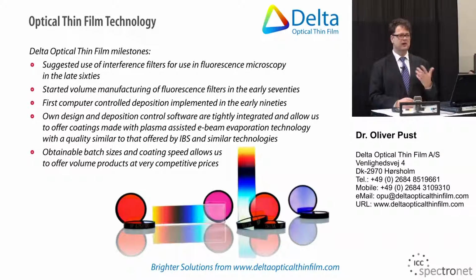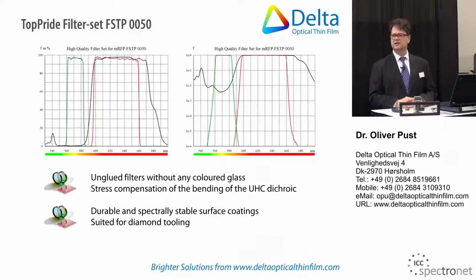Before I show you LVF filters, I can't spare you from seeing some of our high performance fluorescence filter sets. On the left-hand plot you see a typical fluorescence filter set in transmission scale. You can see very high transmission level, very steep edges, very low ripple in the passband. These are actually measured curves. On the right-hand side you see the blocking curve in logarithmic scale, and you can see that we can, without any problem, achieve OD5 or even OD6 blocking if that is required. Also our dichroics are special in the sense that they have a broad blocking range and support at least OD7 blocking for the emission.